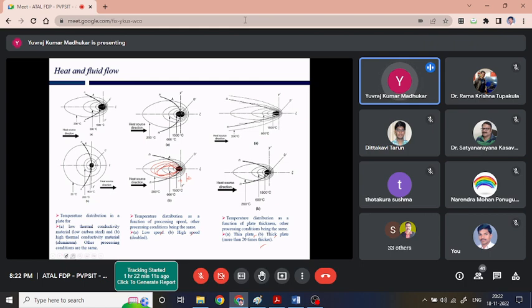If we want to go for the feed-forward control system, then probably we have to put our sensor somewhere around here, which will then communicate to our input source. At such a small distance, specifically when we are talking about the WAAM-based system on which we are generating the arc, and the arc area itself is of the order of nearly 8 to 10 mm, making this kind of arrangement is going to be very difficult. That's why feed-forward control possibly is not a good solution when we go for the WAAM-based online monitoring and control system. It is better to go for the feedback-based control system.